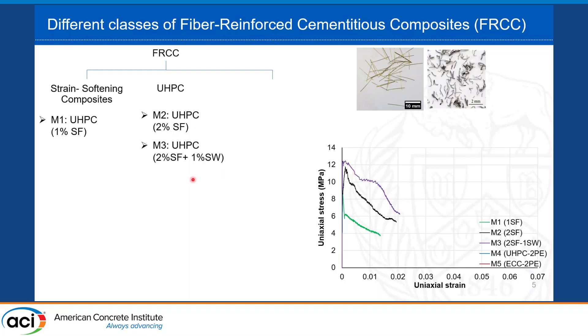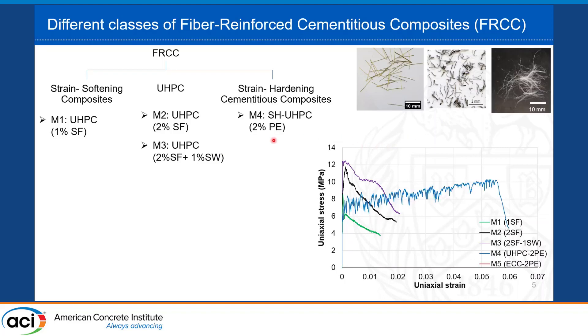The third mix is also UHPC with the same behavior as Mix 2 but higher strength, achieved by adding steel wool to the steel fibers. The steel wool, obtained from recycled steel scrap, has a median length of around 1 mm and acts to bridge micro-cracks in the matrix, reinforcing it and improving fiber-matrix bond. Mix 4 is a strain hardening UHPC using polyethylene fibers, and Mix 5 is ECC — both showing strain hardening behavior but at different strength levels.